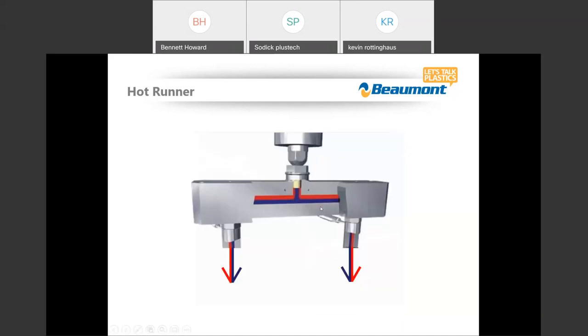And again, when we're talking about hot runners, sometimes people go, well, wait a minute, it's a hot runner. Isn't that plastic always hot? So is there really a frozen layer that develops? There isn't necessarily a frozen layer in a hot runner system, but the laminates abutting the steel wall inside of that manifold are at a relative crawl to the laminates underneath it. So we still have that same shear imbalance, and those laminates are rubbing up against what we would maybe refer to as a no flow layer. So a laminate that's really crawling relative to the laminates underneath it.